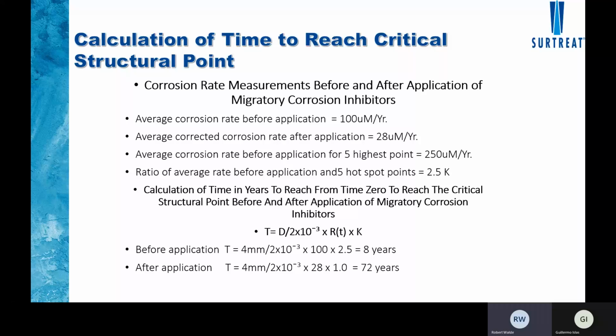So now we see our calculation here. We have T equals 4 millimeters of steel lost, times 100 micrometers per year, times the K factor of 2.5. And this shows that within 8 years, we would see damage. And this is typically what's going on in parking garages. Every 10 years, they come back, do repair work, fix these spots where the hot spots were. 10 years later, guess what? They're back again, rebuilding the garage in 5 to 10 square foot sections every 10 years.